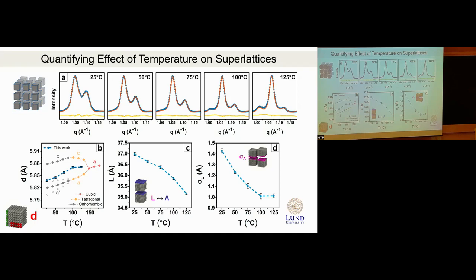Another question. You have this tetragonal low-symmetry structure at low temperature. Are the crystals aligned? The tetragonal defines a symmetry lower than the cubic symmetry. Here this is the symmetry of the structure of the nanocrystal, not the superlattice. Is the structure of one nanocrystal related to the next one, or are they oriented randomly in the 3 possible orientations? We think they are all oriented in the same way because that's why we keep seeing this effect. But your data in B suggests that you see just an average lattice constant. That would suggest that it's maybe not aligned, would it?